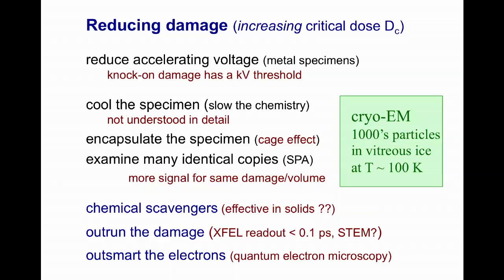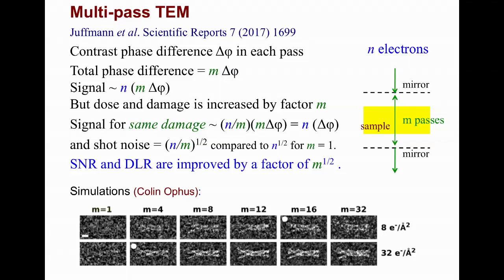Well, how about persuading electrons to act more like waves than particles? That may sound idealistic, but it has given rise to an activity known as quantum electron microscopy, one variant of which is Multipass TEM. Suppose we want to use phase contrast TEM to image a light element specimen, using N electrons. A gated two-mirror device, shown schematically on the right, makes each electron pass m times through the sample before the electron is released and recorded in the image plane.